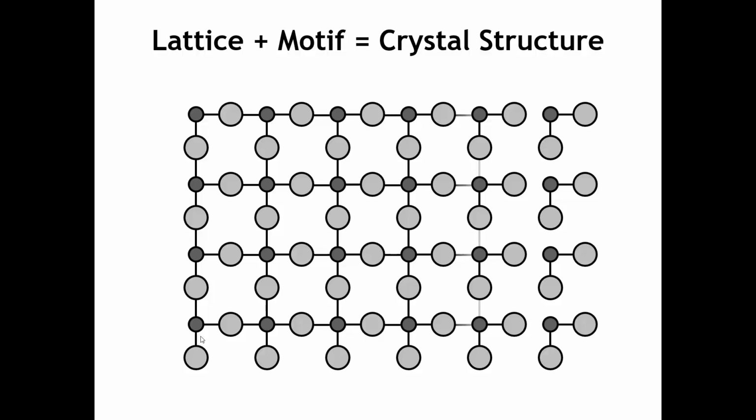And so you see that I would have this kind of connectivity of my crystal structure. So each copper would be surrounded by 4 oxygens in a square planar environment, and each oxygen is surrounded by 2 coppers in a linear environment. Okay, and so this CuO2 layer, in fact, is a really important building block of the cuprate high Tc superconductors